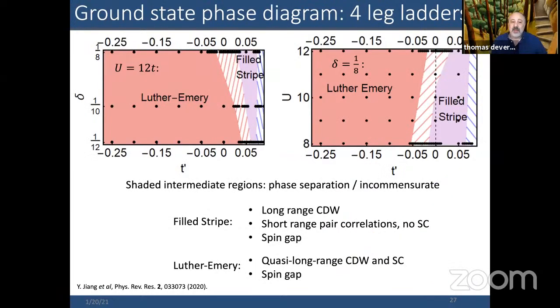And in fact, you can show as you change doping or change T prime that the filled stripe state, the non-superconducting filled stripe state, gives way after a period of phase separation to a large region that is this Luther-Emery liquid, which is characterized by having half-filled stripes and long range, quasi-long range, or as best you can in quasi-one-dimensional, charge density wave order and superconducting order, along with a sizable spin gap.